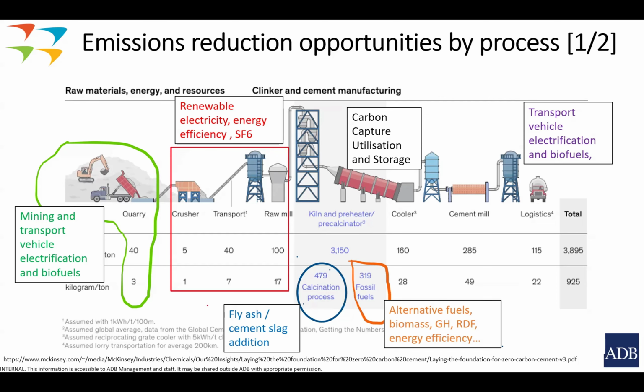Then comes the most important aspect, which is the kiln and preheater. The options over here: one needs to see what the fly ash blending is, that is one of the things, or slag addition to cement, steel industry slag addition, that is another thing that can happen. The importance of this is that 50 to 60% of emission in cement making is actually coming from the inherent cement making process, which is CaCO3 disintegrating into CO2 plus CaO. So the more fly ash or slag you add, the more it will tend to reduce the calcination process, and that is how we will be able to reduce it.